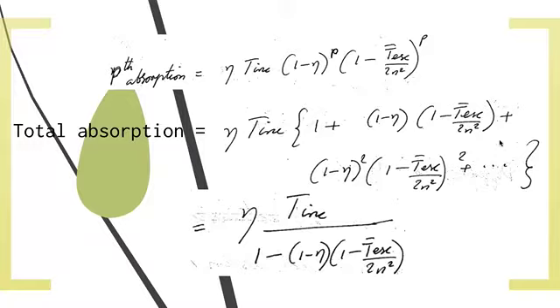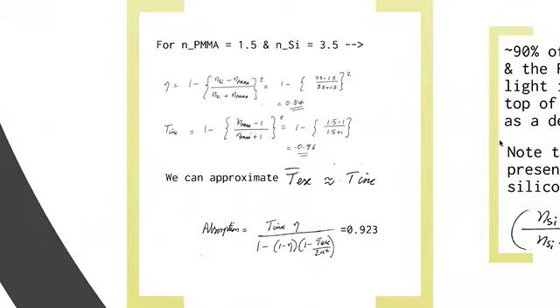Okay. That's really simple. So that now gives us how much light is absorbed within silicon in the presence of an anti-reflection coating. Now we can throw in some rough numbers. For PMMA, eta is 1 minus that difference, and the difference factor is squared. We end up with something like 84%. And T incident is 96% because it's going from air into the plastic. Okay, you can plug in those numbers. So eta is 84%.